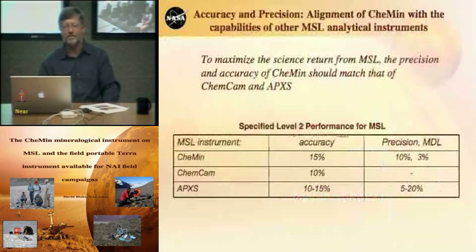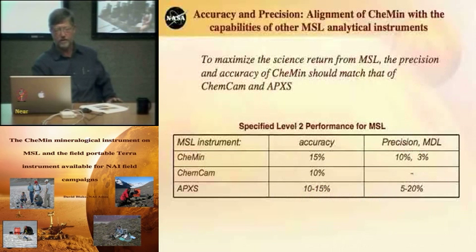Now that we know what full range and all that is necessary, what kind of accuracy and precision do we want? This shows the accuracy of the ChemCam instrument and the APXS and the precision, and we picked an accuracy of about 15% of the amount present. We can actually do better than that, but this is our requirement. This is what we have to show in order to be fully responsive to our contract. And a 10% precision with a minimum detection limit of about 3%. And we can actually do better than this, but this is what we signed up for.